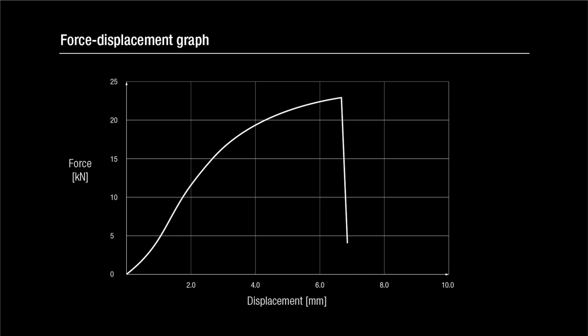The force displacement graph shows an initial linear elastic response. In a clear wood beam with no defects, the tensile strength is much higher than the compressive strength, so as the wood in the compressive zone begins to crush, the bending behaviour becomes non-linear.